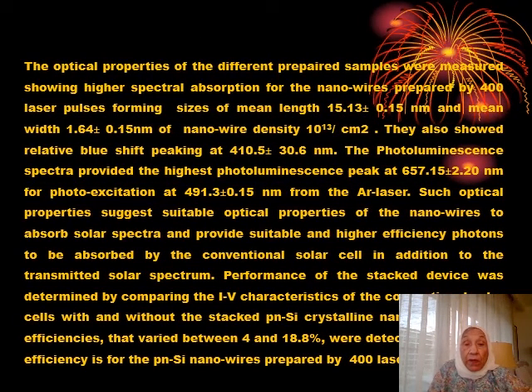The optical properties of the different prepared samples were measured, showing higher spectral absorption for the nanowires prepared by 400 laser pulses, forming sizes of mean length of 15.13 plus or minus 0.15 nanometer, and mean width of 1.64 plus or minus 0.15 nanometer, of nanowire density 10 to 13 per centimeter square. They also showed relative blue shift peaking at 410.5 plus or minus 30.6 nanometer.